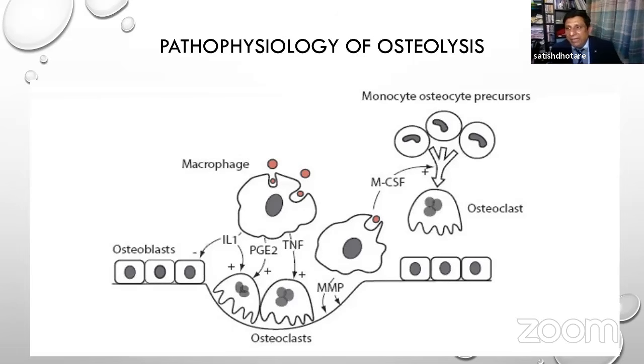So these wear debris or wear particles, be it from polyethylene, which is most common, or metal debris, are of different sizes, and the number and volume of wear debris is proportional to the size of the particles. And the size of the particles is between 0.1 to 10 micrometer. And the macrophages get activated with these small debris particles. And if the size of the particle is in the range of 0.2 to 0.5 micrometer, then macrophages get more activated because they can engulf those size particles very easily.